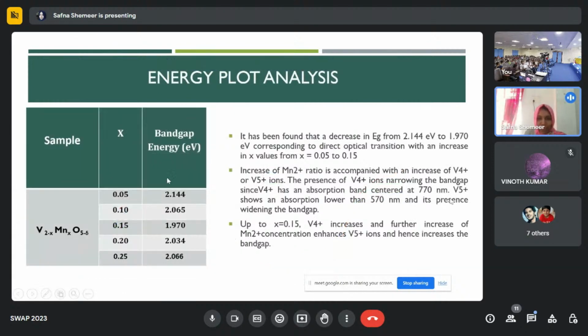From the energy plot analysis, it has been found that a decreasing energy bandgap is observed up to the mole fraction 0.15. With further increase in mole fraction, a small increase in the bandgap energy is noticed. An increase of Mn2+ ions is accompanied with an increase of V4+ or V5+ ions. The presence of V4+ ions narrows the bandgap, and the presence of V5+ ions widens the bandgap, because V4+ has an absorption band centered at 770 nanometers, but for V5+ it is lower than 570 nanometers.